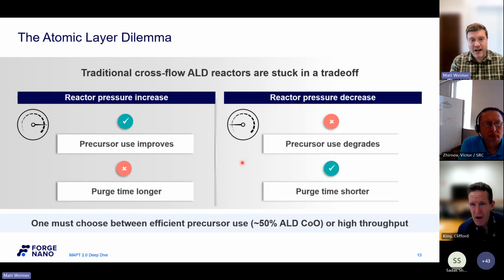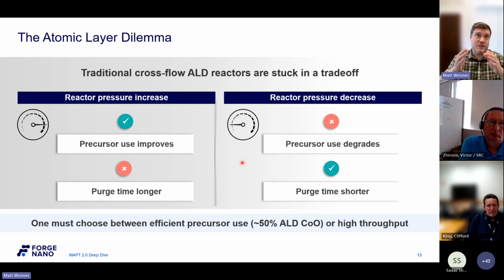So in my opinion, the main reason for this is when you run ALD, you have to choose a pressure regime, either a high pressure regime where you use precursor more efficiently, or a low pressure regime where your purge is more efficient. And if you think about this from a gas residence time, at the higher pressure, the precursor molecules move through the reactor more slowly. Those diffusion path lengths from your laminar flow lines are quite simply larger, and it's easier to get a uniform ALD film. But it takes longer to move precursor molecules out of the chamber because of that gas residence time. So if you want to move faster, you go to a low pressure regime. And this is typically how it's done in the 300 millimeter space. And you just deal with those extra precursor inefficiencies, which is why that 50% mark from ASM was such a, oh, that's kind of impressive.